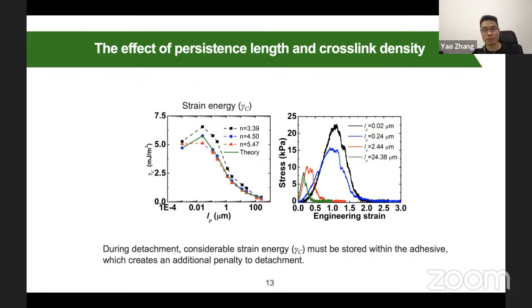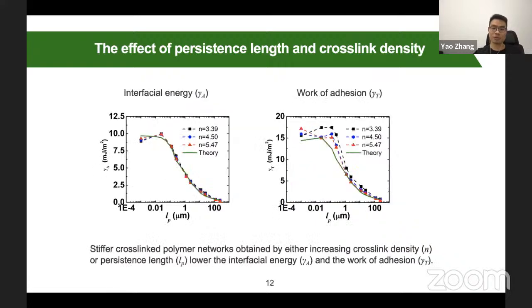So we look at the stress-strain curve. When you detach the network from the surface using the force, we get this stress-strain curve. Then we can calculate the strain energy. The strain energy is the area under the stress-strain curve. When you calculate the strain energy, you can see that its magnitude is very close to the difference between the work of adhesion and the interfacial energy. So this means that if you use a force to detach the network from the surface, first you have to overcome the interfacial energy between the network and the surface.